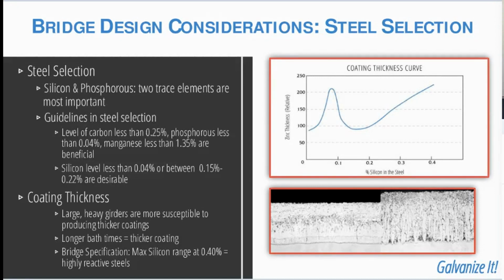Many steel grades common in the bridge market have a wider restraint on actual silicon content, and as a result, these steels tend to be more reactive. This isn't necessarily a problem, except in cases where there may be a potential for excessively thick coatings above 8 to 10 mils. These excessively thick coatings could be susceptible to delamination or flaking. And where silicon content is expected to be relatively high, abrasive blasting before galvanizing can be used to limit the coating growth on these steels to about 10 mils. Otherwise, staying within these recommended ranges will provide you coatings that are going to be more typical in appearance.